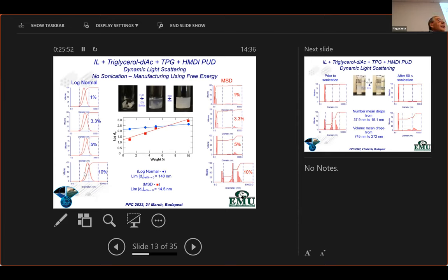So this illustrates that these kinds of materials are really in a supermolecular equilibrium, and they're supermolecules because as you dilute them, those shallow aggregates, or attractive potential minima, are depopulated to form more and more smaller particles. And I should stress these are all volume weighted distributions rather than number frequency distributions. If I would show number frequency data, they mostly look like this, but the volume weighting stresses the larger particles, which dominate the physical appearance of scattering.